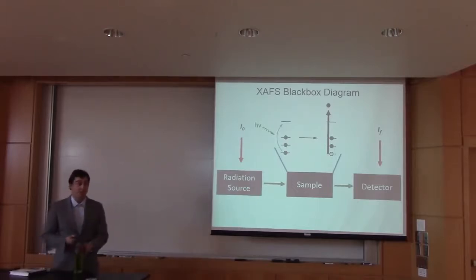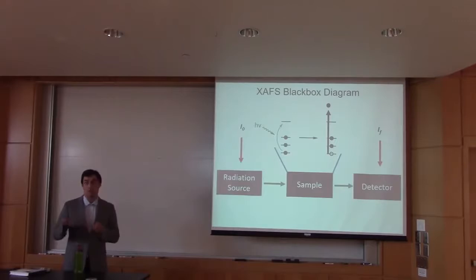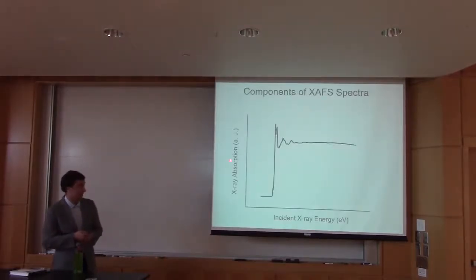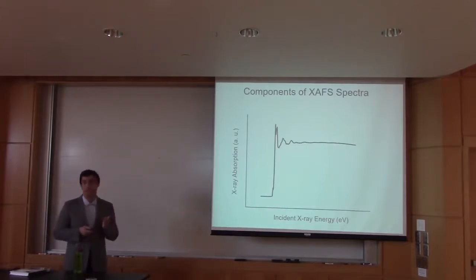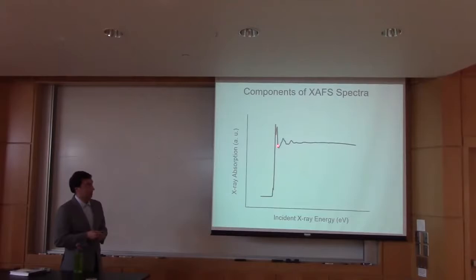That's going to produce a spectra, which is going to show us absorption as a function of energy, and looks something like this, where we have X-ray absorption plotted against energy. And what we see as we slowly increase the energy, we have not a lot occurring in the absorption until we hit a certain point, and this is called the edge, where we have hit the point where that absorbing atom is going to be absorbing that energy and ejecting a photoelectron. We're going to go out and then have the absorption decrease and kind of oscillate out.